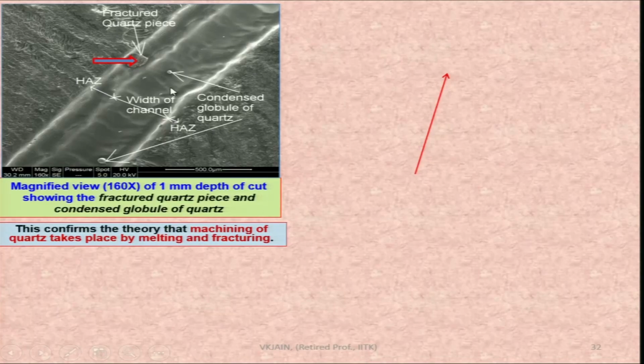This is the micro channel machined by using electrochemical spark micromachining, and this is the fractured parts of the quartz. This is not the globule. Globule is here. This is due to the melting of the material and then getting solidified. This is globule here, melting and solidification, but this is the fractured part. So, it simply means that other regions are also involved. So, this confirms the theory that machining of quartz takes place by melting and fracturing, both, not only by melting or melting and vaporization and fracturing.